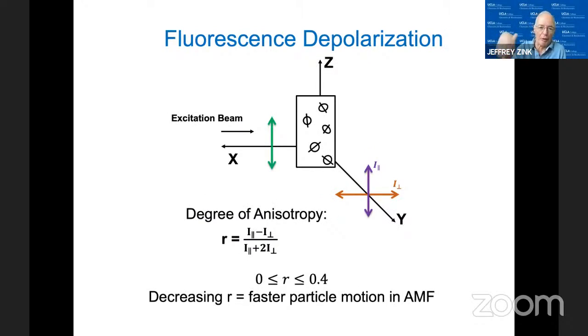Now, we were very interested in determining which mechanism we have. We want to know if our particles are moving or if it's just the electrons that are moving. A way of doing that is to use fluorescence depolarization. This is an optical technique. Basically, the idea is that if the system moves after the photon comes in, the direction of the polarization will also change. If the system is static, the polarization won't change. And that degree of anisotropy, R, the difference between the parallel and perpendicular light, is a measure of how much motion there is. So a decreasing R means fast particle motion under the alternating magnetic field. That would be the motion of the particle causing the orientation to change.